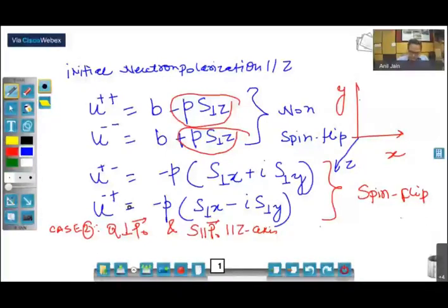Suppose Q is in the horizontal scattering plane, the polarization of your incident neutron beam is vertical, and suppose this is the direction of Z, and that is the direction of S also. In this case, all your magnetic scattering will go to non-spin flip.